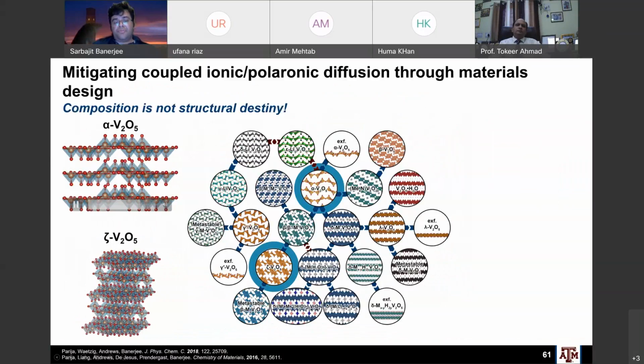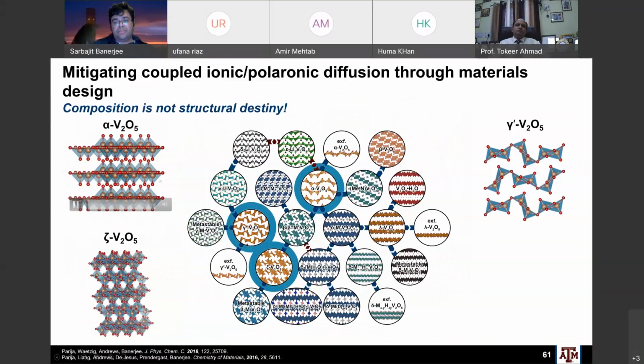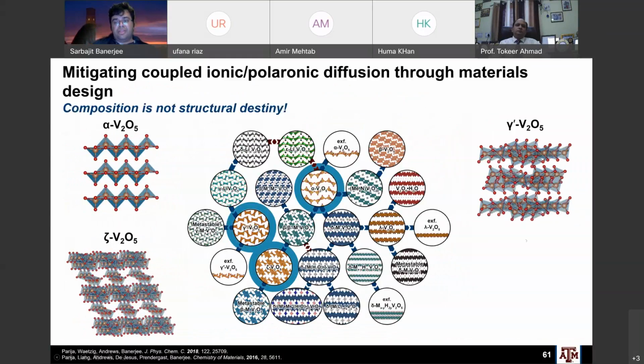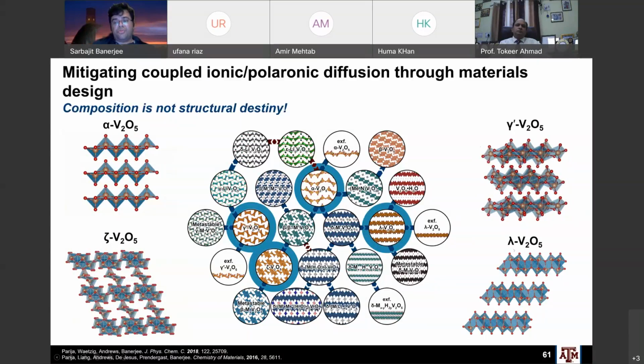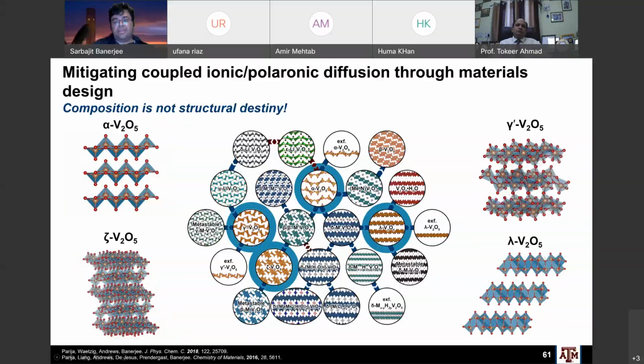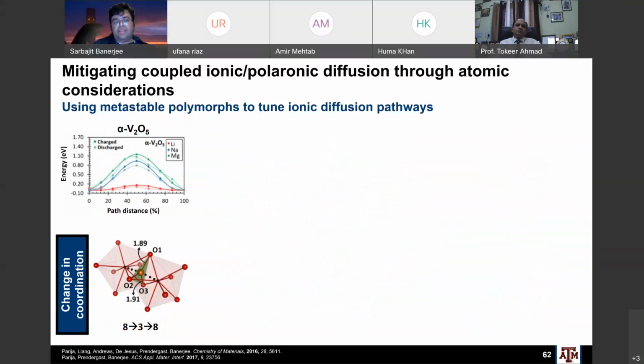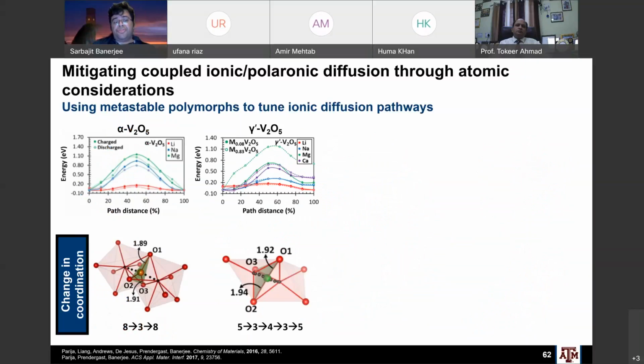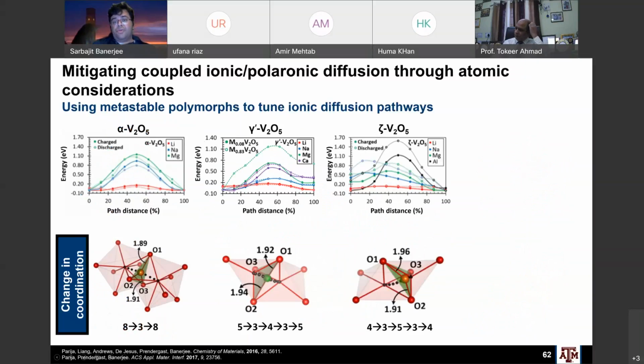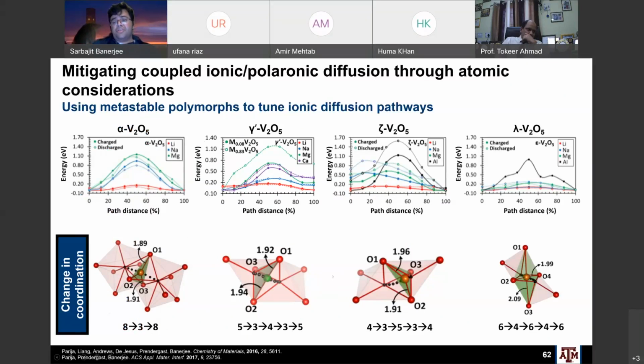These two are exactly polymorphic to each other, all right? Also, this puckered structure, gamma V2O5, and then here's a new structure, which I don't have an animation for, which is a double-layered lambda V2O5, okay? And so the point is that by going to these other polymorphs, in alpha V2O5, we had 8 to 3 to 8, and I told you that was a problem. For instance, in this gamma prime V2O5, we go to 5, 3, 4, 3, 5, or in the case of zeta V2O5, 4, 3, 5, 3, 4. So much smaller changes in coordination environment, in coordination number, so the barriers tend to be much smaller.